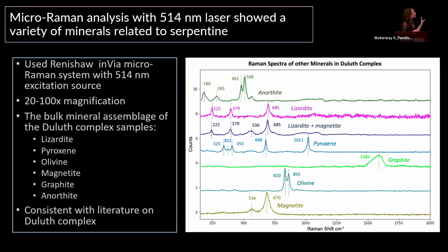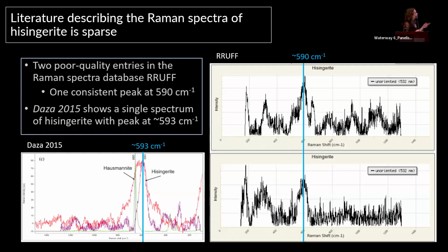And so we started looking, and I found many different minerals in these samples that tracked very well with the literature of the Duluth complex. So we found anorthite, lizardite, magnetite, pyroxene, graphite, and olivine, all very beautiful spectra, but nothing that looked like it could be hisingerite or had a band in the last slide. You can see it's about 590 where there's consistency.